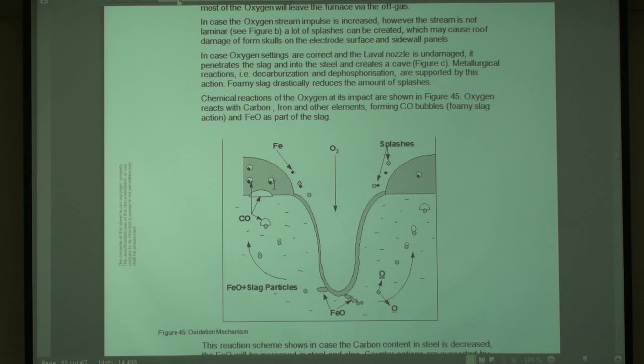Yeah? But if you have high volatile, the carbon is coming in the hot atmosphere in the furnace, and you start cracking, as he said, the volatiles of the carbon. And the carbon cannot penetrate in the slag because the gas generation avoids that the carbon is penetrating. Or even if the carbon is penetrating into the slag, the carbon grain is surrounded by a bubble of these volatiles. And the carbon has no more, let's say, contact with the FeO. So it doesn't create additional CO. Yeah? So you may do this experiment sometime, and you will see that the foam is not created by the high volatile carbon.